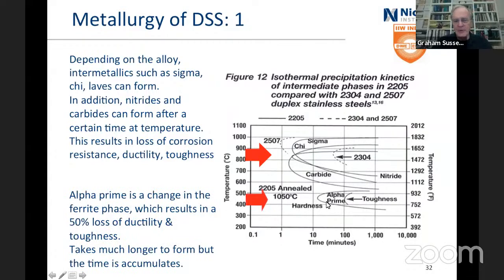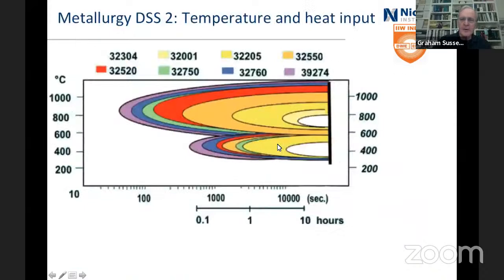Alpha prime, this is down here, centered at, actually it's a bit above 475. Oh, that's F, sorry, 475 over here. These curves here are having lost 50% of the hardness or 50% of the toughness, but it takes 12 minutes for that and 100 minutes for losing the toughness. So it's a lot slower than particularly the sigma phase formation. And it happens for all of the alloys.